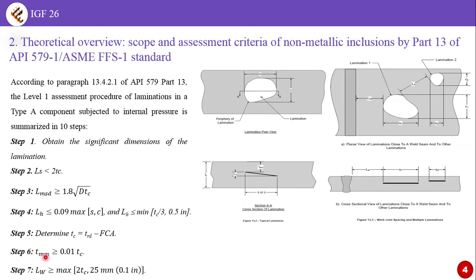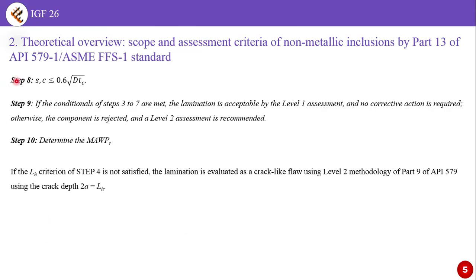Step 6 is verifying this criterion, where the minimum measured thickness, or TMM, has to be greater than or equal to this value. If this criterion is satisfied, we can go to step 7 to investigate the distance between the lamination and the weld joint or weld metal. If this equation is accepted, we can go to step 8 to study these criteria, where the dimensions of laminations have to be less than or equal to this value.